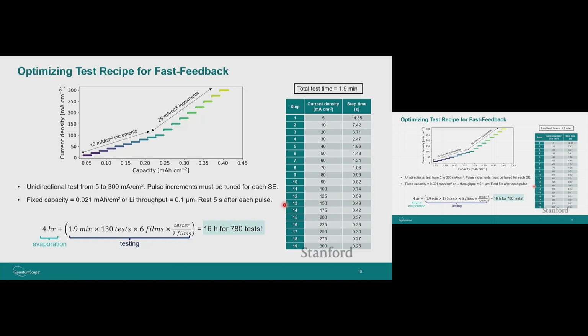So in that analogy, we do the same thing with current. We apply current for a certain amount of time, monitor to see if the material fails. If not, then we increase the current. So this shows a little bit about how we've chosen those current density increments, how much current density we pass at each step before we increase. And so this is the simple math to get to almost 1,000 data points in 16 hours.